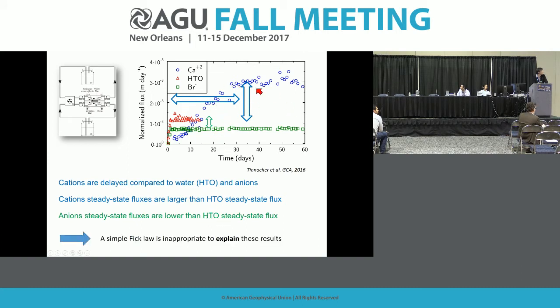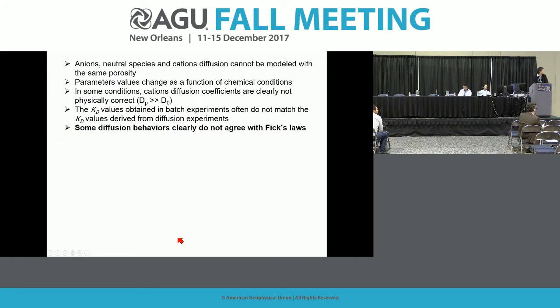And so if you want to explain all of this altogether with the same model, in fact, you will go to the conclusion that a simple Fickian model is not appropriate to explain the results. Of course, you can fit the result with a very simple Fickian model, but you cannot explain the result as a whole. So, in fact, we have ample evidence of this problem. Anions, neutral species, and cations do not have access to the same porosity, so you have to change your porosity as a function of species if you use just a Fickian model. The parameter values change as a function of chemical conditions, so a Fickian model cannot account for this change.